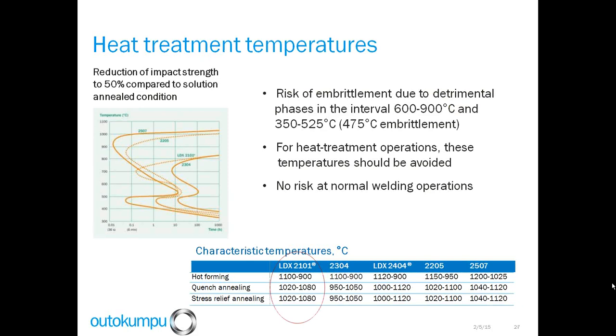These are some of the characteristic heat treatment temperatures for hot forming, quench annealing, and stress relief annealing. You can see the risk of embrittlement for these materials. Basically, you don't want to expose them to the 900 to 350 degrees C range. You have different things precipitating out that affect the fracture toughness as well as corrosion resistance at these temperatures.